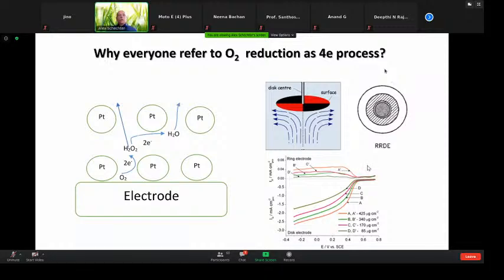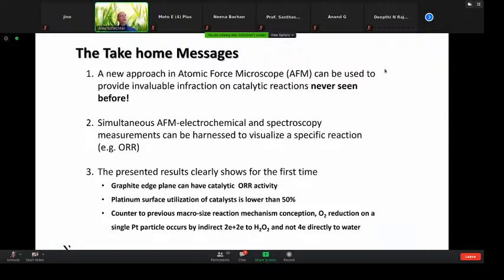So what is the take-home message? We were able to show a new approach for studying electrochemical catalysis simultaneously in a way that was never envisioned before, never possible before, in a very high resolution. The results clearly show that the graphite edge plane is responsible for oxygen reduction. This was assumed but never seen before. Everyone knows that some defects can improve it. It was shown before, but seeing it with your own eyes and seeing where exactly and which defect actually promotes the reaction more, that was not seen.